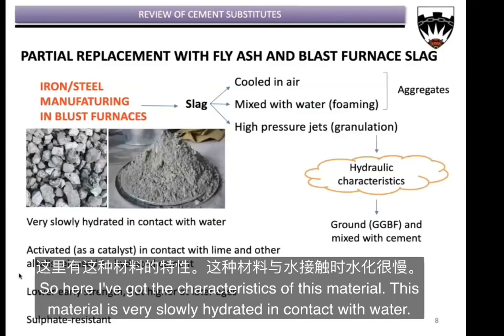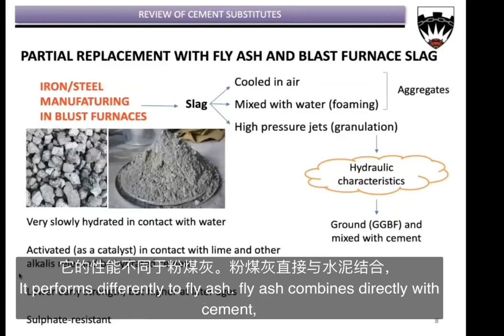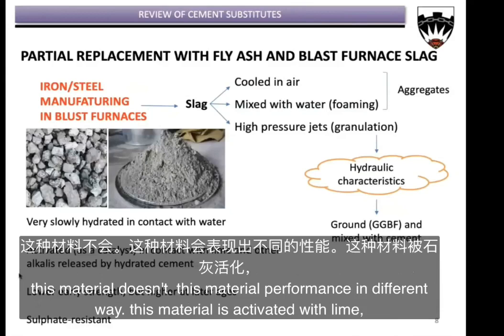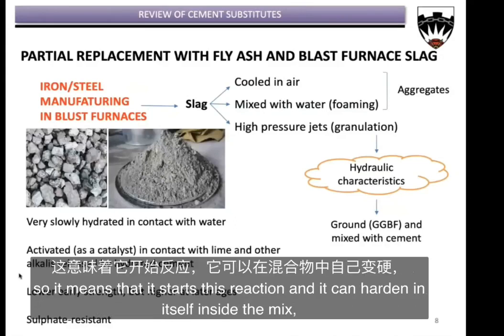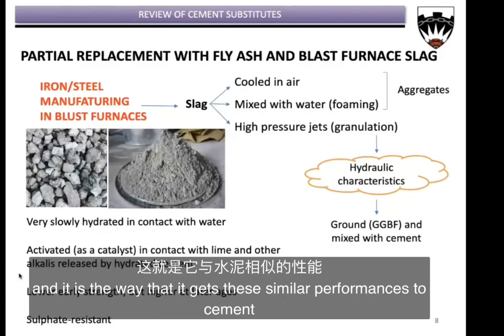So, characteristics of this material. Well, this material hydrates very slowly in contact with water. It performs differently to fly ash, right? Fly ash combines directly with cement. This material doesn't. This material performs in a different way. What happens is that this material is activated with lime. So it starts this reaction, and it can harden by itself inside the mix, right? And that is the way it gets similar performance to cement.